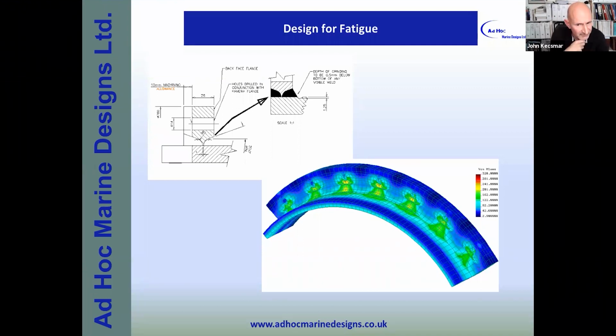I then took this to the next stage because we have to weld the flange, which takes the mating surface between the actual jet bucket itself to the duct. So here you can see there is a solid model of the flange, which is then welded to the actual duct itself. And I modeled the weld and I calculated how to apply the bolt forces onto this flange and then worked out what the stress is. But as you can see here, the stress is actually quite high.